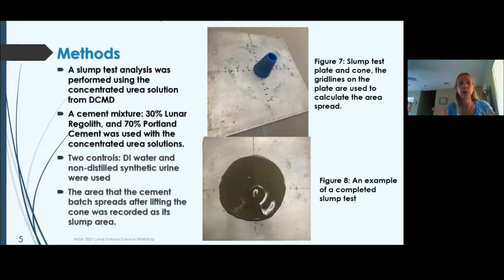And you need to have a certain amount of workability in order to mold the cement to where you want it to be. We didn't have enough material to use a big metal cone, so we 3D printed a small cone, and we would pull that off and see how far the cement spread to determine how workable the mixture was. We used two controls in our study.